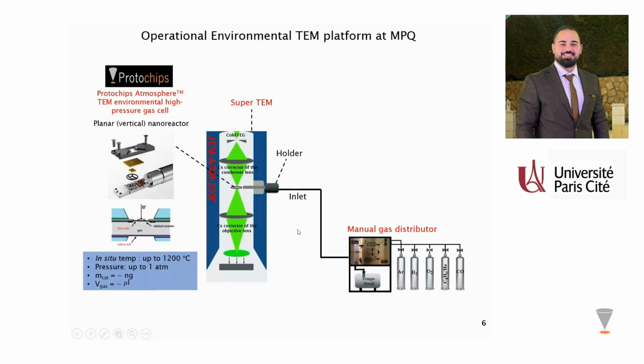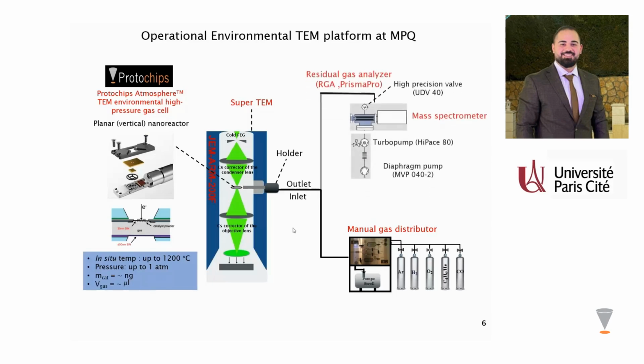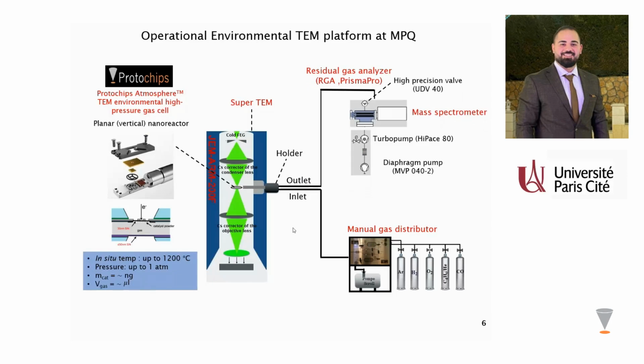Also, to achieve operando condition, we coupled the outlet of the holder to a residual gas analyzer having a mass spectrometer, which allows us to calculate the composition of the reactant and product gas. So despite the different limitations of this homemade coupled setup, we succeeded in overcoming all the limitations and keeping the atomic resolution of the Super TEM in complex, operando, and in situ conditions.